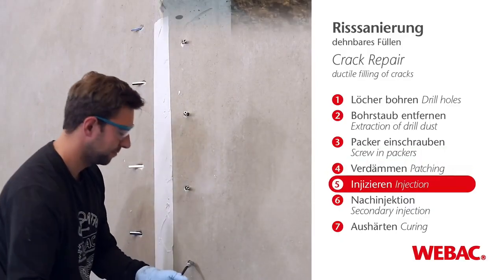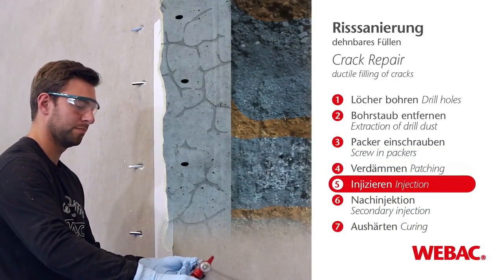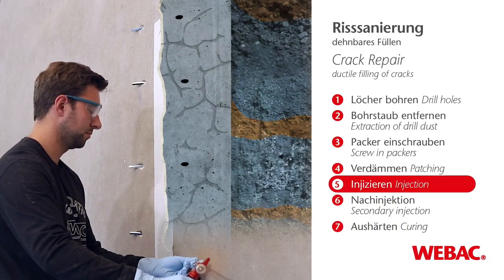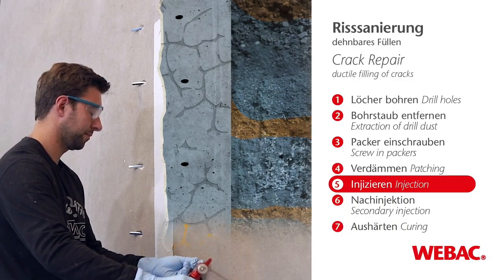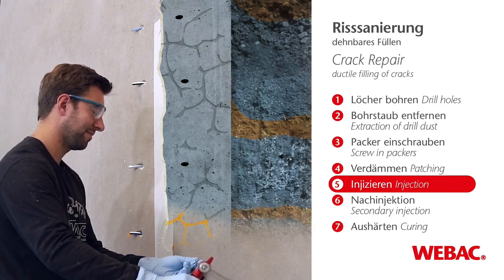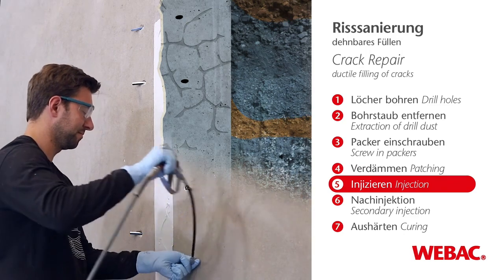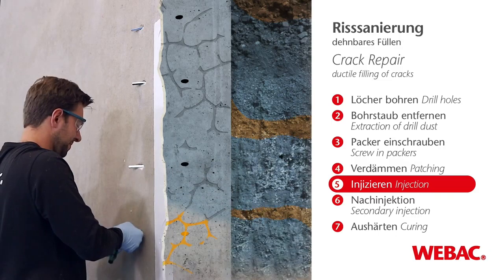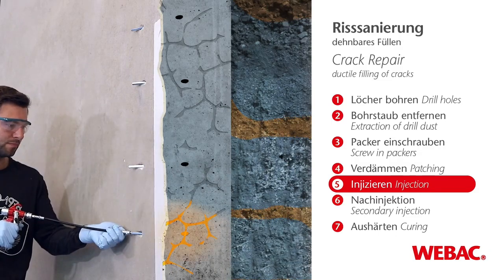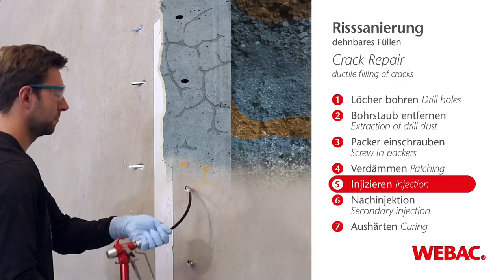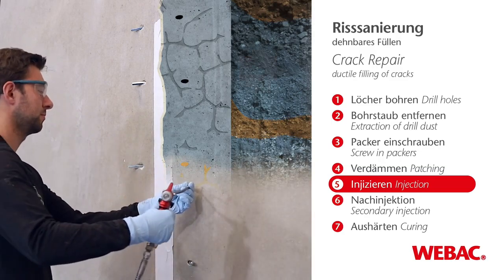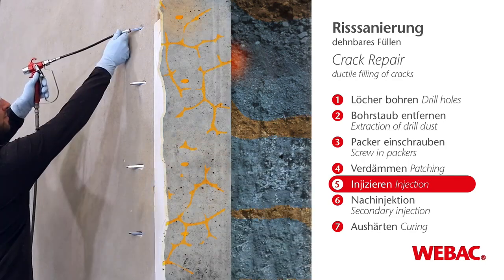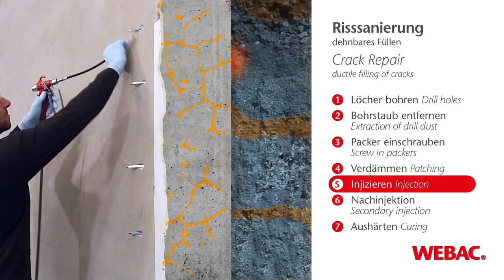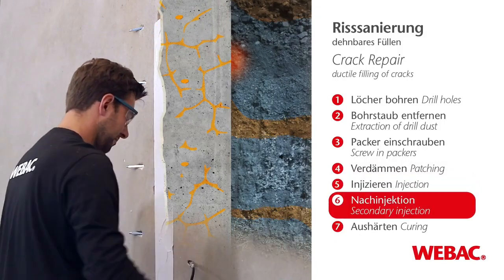Material is mixed and filled into the pump. And then the injection process starts. Again, always from the lower part to the upper part, and you have seen it in the video. Sometimes water which is in the crack comes out of the next packer, and this is when you are injecting for a longer time. If you have filled the complete crack, you see the material coming out